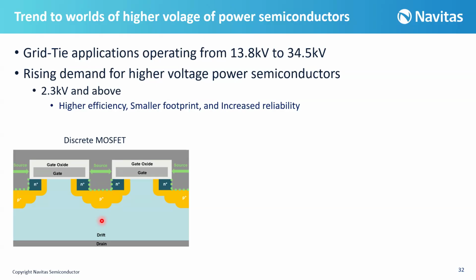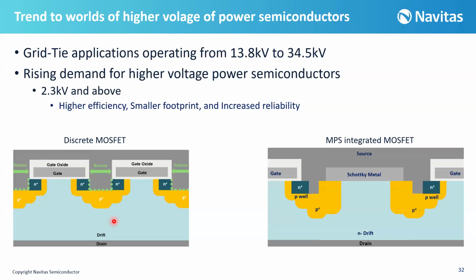So suppose that we have a very thick drift layer, and these stacking faults are growing at a 4-degree angle. By increasing the thickness, we have more area that is affected by these stacking faults, and finally we have the bipolar degradation. One way to overcome this issue is, instead of using the body diode in this PN junction or PIN diode, we can integrate the Schottky diodes or JBS or MPS inside the MOSFET.